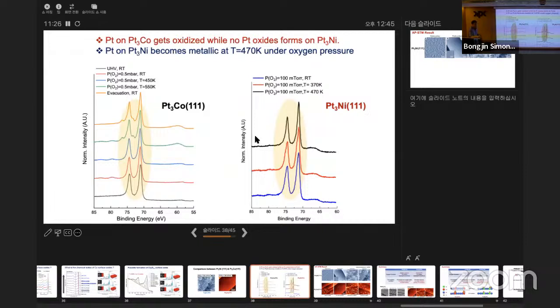And this is the big difference of these two systems, which we think is that in platinum-3 cobalt, the cobalt comes up to the surface and forms an oxide that is actually very stable. And that actually creates a lot of defects. This is still, we are actually guessing. And that defect creates enough space that disturbs the platinum, and the platinum gets oxidized. Nickel, no. With nickel, the platinum is just coming up to the surface, but that oxide is not stable enough.